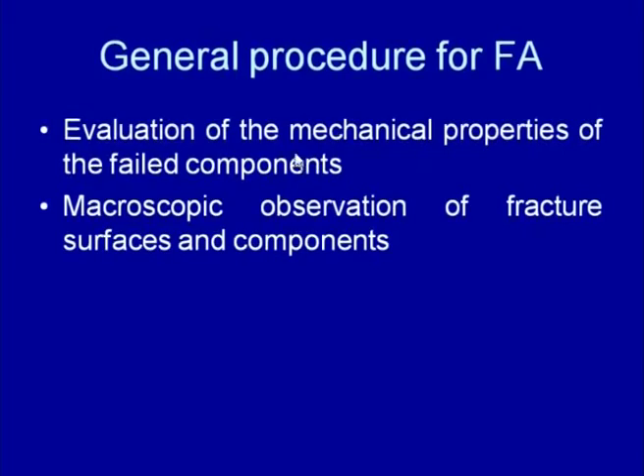or if the component is deficient, because if discontinuities are present even in locations away from the fracture surface, that will indicate that the material itself was deficient or had discontinuities. So to establish the presence of any discontinuity, we can perform the non-destructive testing on the samples which have been taken from both locations, whether close to the fracture surface or away from the fracture surface. Then evaluation of the mechanical properties of the failed component.